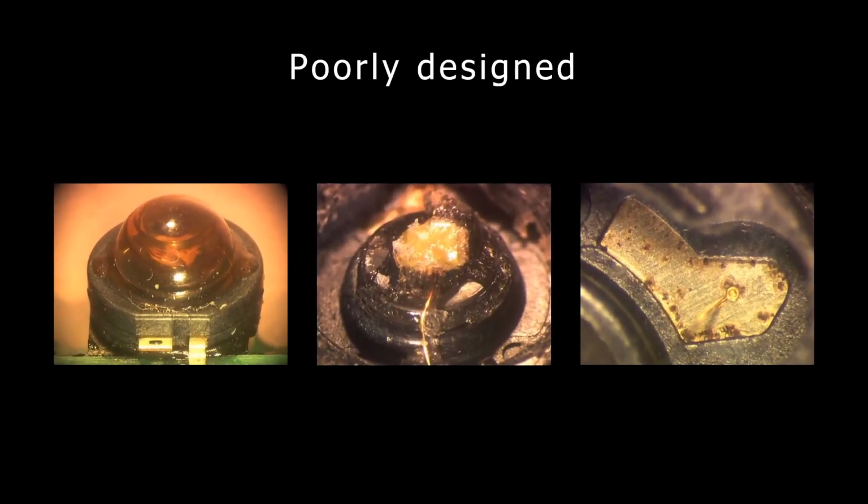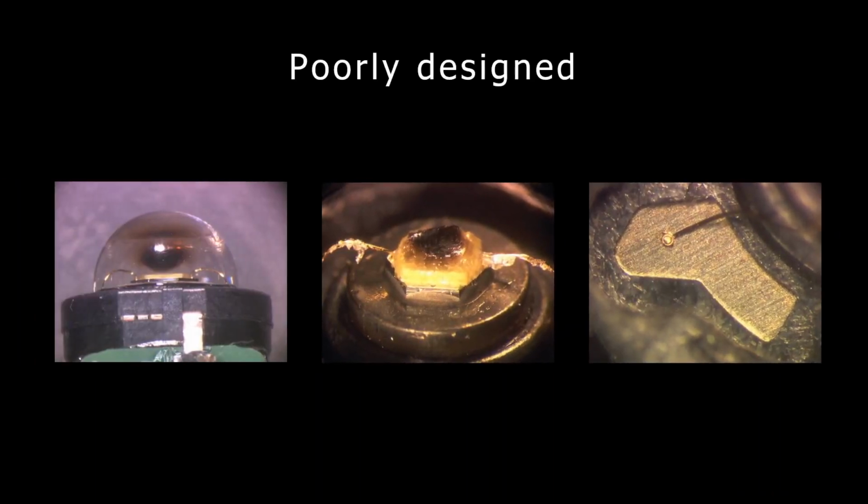This LED was not heat sinked properly because an improper heat sink material was used. This caused the LED to overheat, which resulted in the darkening of the silicone and decomposition of the silicone, which then became corrosive and attacked the metallization. This is an additional flaw in the same design. This LED was overdriven. Overdriving carbonized the inner lens above the LED, which shorted the package. No metal corrosion is observed here.